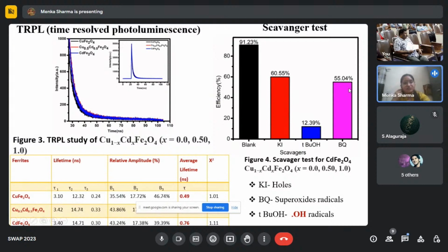We have performed the scavenger study in which we have used different types of scavengers. KI, basically potassium iodide, is used to trap holes, and benzoquinone is used to trap superoxide radicals. In the case of tertiary butanol, which is used to trap hydroxyl radicals, the degradation efficiency is minimum. So that is why we can say that the hydroxyl radicals are the major active species in the degradation of